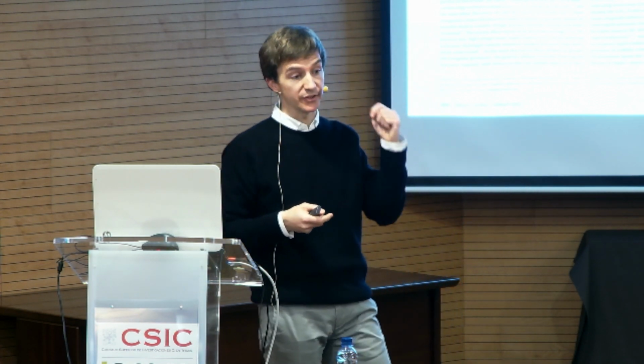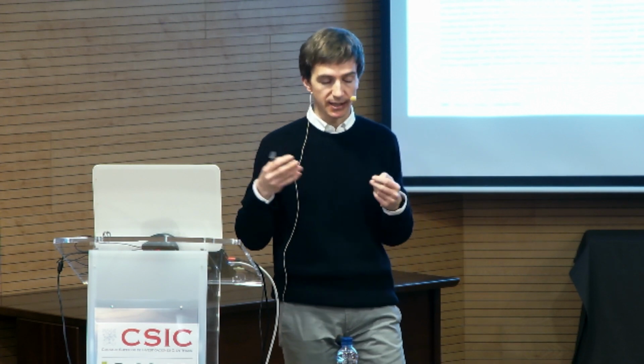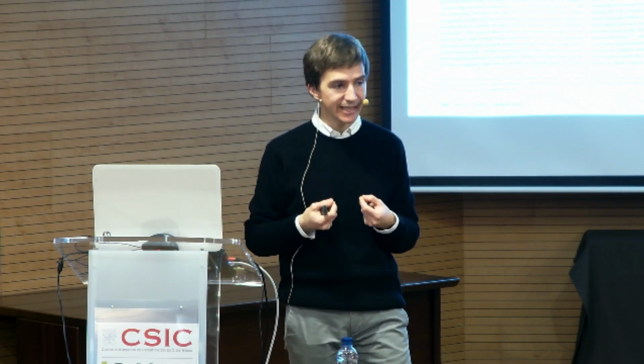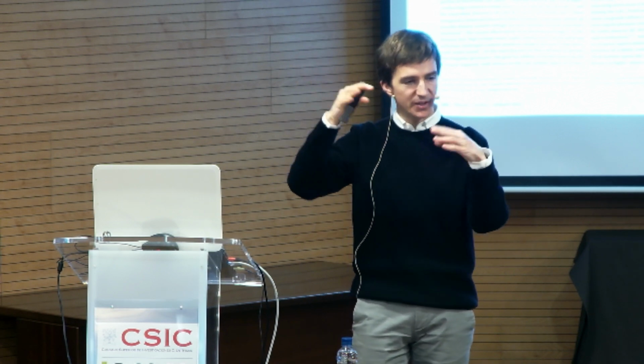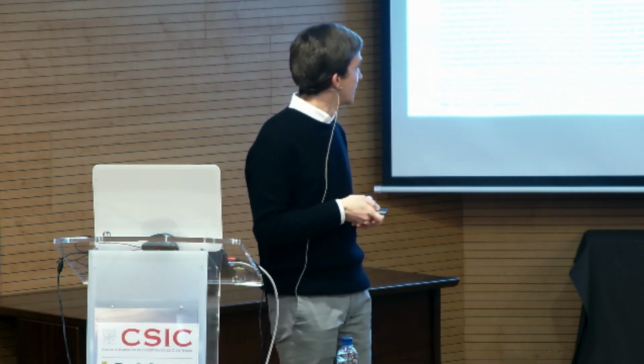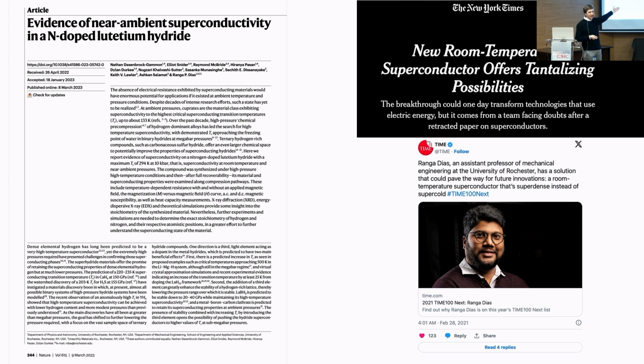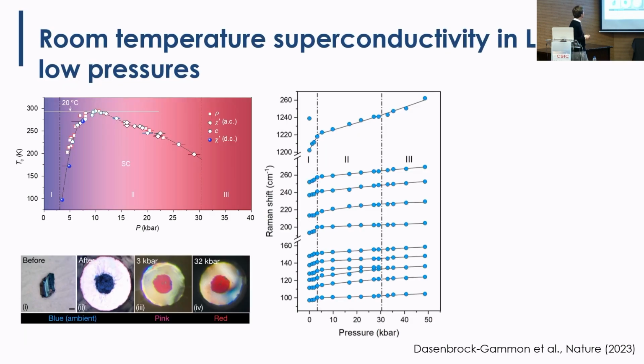It was not so unexpected. But that paper had been retracted because there were some problems on the subtraction of the data in the magnetic measurements. Apparently the data that was claimed to be the measured data was not the measured data, but was processed with a somehow in-house way of subtracting the noise. There were controversies about that. But still, he had been selected by Time magazine as one of the big important people, so he had a very strong recognition in the community, I would say. So these are the evidences, okay? It's very surprising. They were measuring several things.